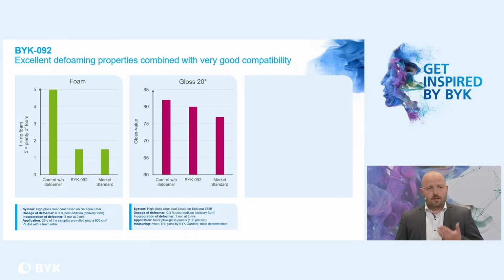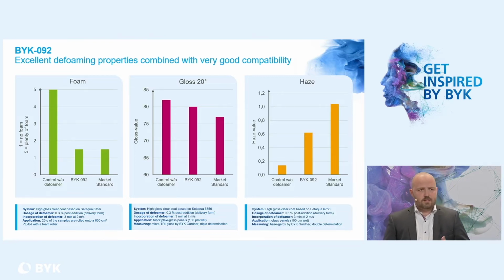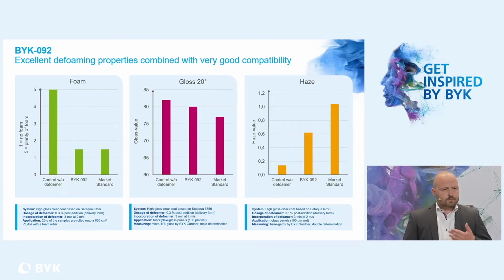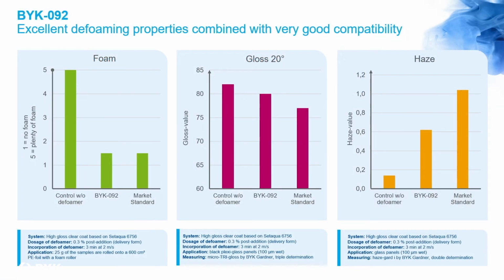But when you look at the gloss and the haze of the coating, you can clearly see differences. So always the control without the defoamer is the best, and the BYK 092 has a very, very minor influence, while the influence of the market standard is a lot higher. So as in our wood coating systems, also in the architectural coating system, the BYK 092 shows outstanding transparency and really no haze.